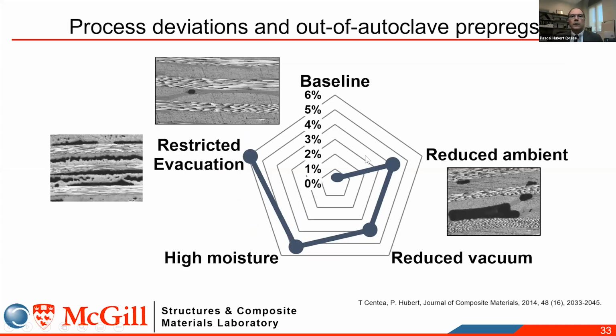We know that if we use, let's say, out-of-autoclave prepreg to do a repair, and we make the repair in the best condition possible, you get very low porosity. So we can control the process, and you get good quality parts. As soon as you deviate from those conditions, let's say now you don't have such a good vacuum in your vacuum bag, you are in a moist environment, you cannot extract all the air properly, you start to see a degradation of the quality of the composite.